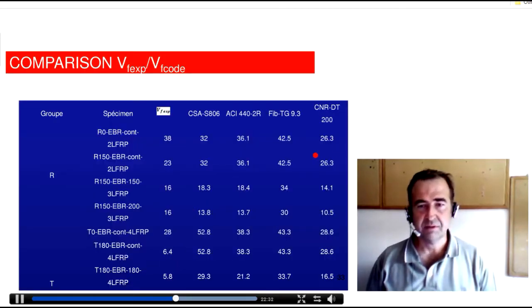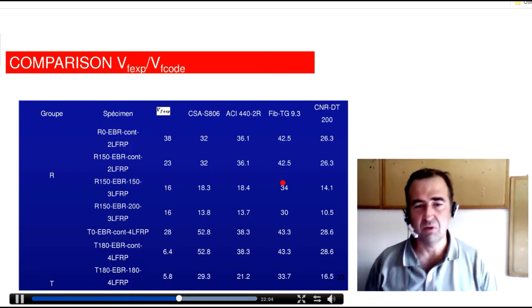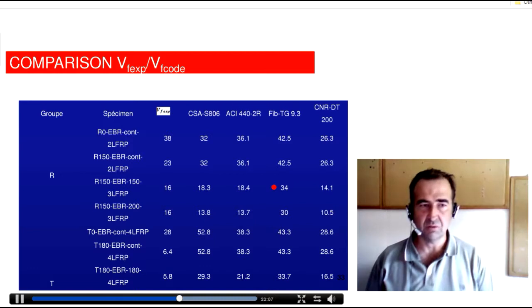We then compare these results with the different ones coming from literature, using CSA or ACI or FIB or CNR bulletin, and the failure we expect to get with the flax fibers using the mechanical properties. And in any case, more or less only with the FIB bulletin, the estimation is very nice. With this calculation method, the load expected is higher than the one we get really in experiments. But in most of the cases, generally, the level of load is calculated as the one we have with carbon fibers.